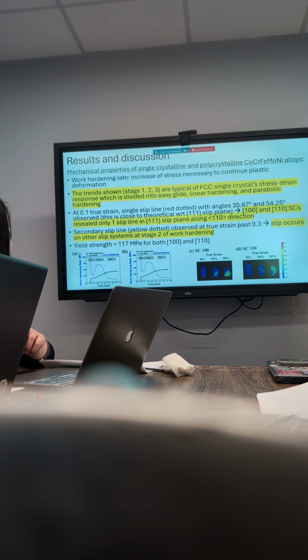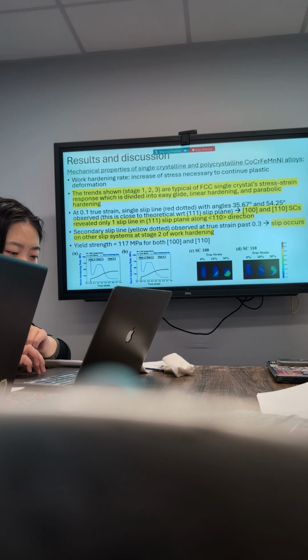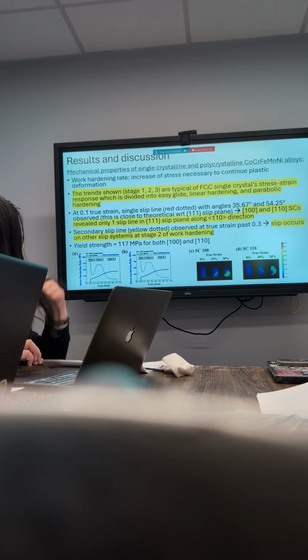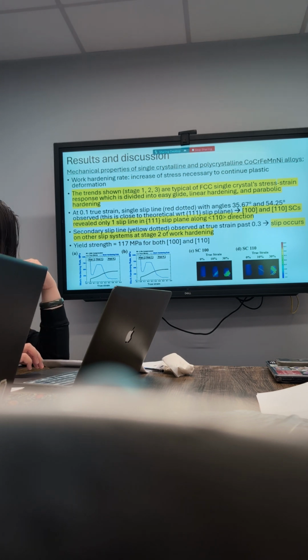Versus in the single crystals, okay, so single crystal 100 and then 110, they revealed only one slip line versus 2 slip lines. And then they found a secondary slip line, which is the yellow dotted line at 0.3 true strain. So clearly there are 2 different steps happening, which means this slip is occurring at another slip system at the second stage of the work hardening. So they're trying to show that for these different stages, easy glide, linear hardening, parabolic hardening, different slips are happening in different slip systems, at different times. And then they found that the yield strength is 117 megapascal for both 100 and 110 single crystals.